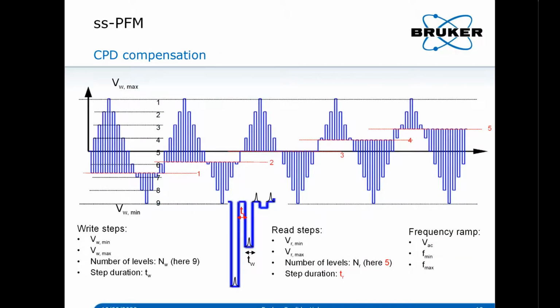And we try to move it a bit further by introducing a DC offset for the reading voltage. As we mentioned many times, the electrostatic interaction can be a very important and almost unavoidable artifact in normal PFM measurements. By introducing this reading DC offset into the switching spectroscopy PFM, we can compensate the CPD between the tip and the sample. And once you don't have this CPD, of course, you don't have any electrostatic interaction force, theoretically speaking. So this is a way to remove or completely screen out the electrostatic interaction involvement in the piezo response. From there, people developed other modes called contact mode KPFM, which will be another topic.